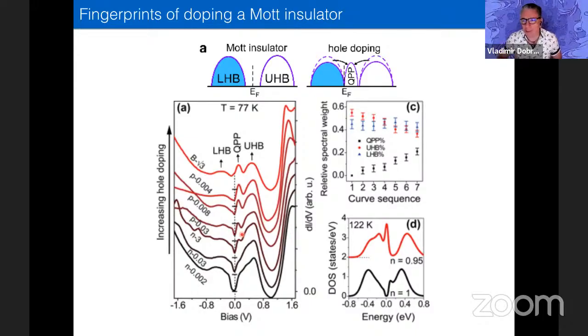So what is your feeling? Is this a system that will be strongly correlated in this regime, in the sense that the effective mass should be substantial, that the quasiparticle weight is significantly smaller than 1? That's why we'd expect these healing effects on QPI to be significant. Yeah. But if Z is close to 1, then probably it doesn't matter. So what's your feeling about that in this system?